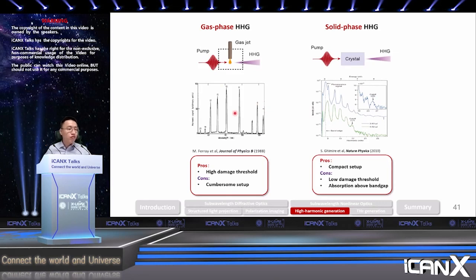One of the main reasons for that is that all those inert gases have quite a high damage threshold, so you can use a very strong laser to pump it and generate harmonic light up to hundreds or even thousands of orders. But one of the problems with gas-phase high harmonic generation is that the setup is quite cumbersome.